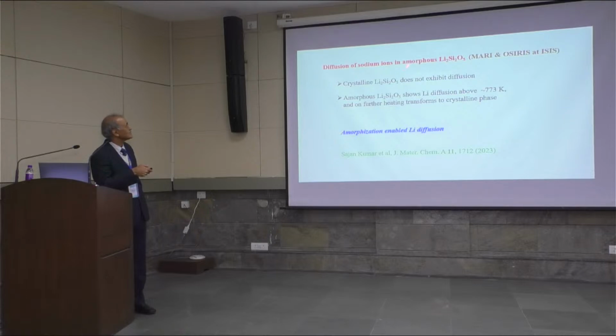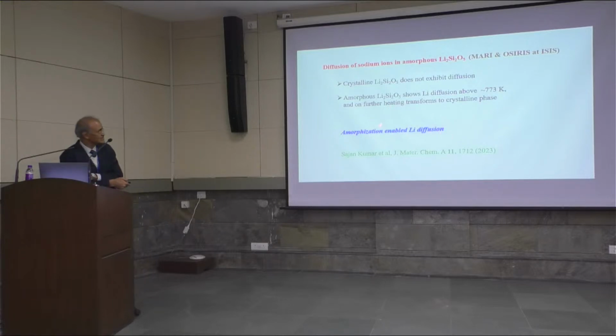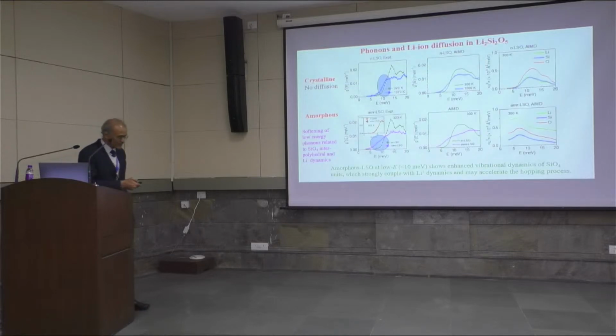There are some experiments done at ISIS, that is the Rutherford Appleton Laboratory in Oxford. What is known is that the crystalline material does not exhibit diffusion, but the amorphous material shows diffusion at some higher temperature, and on further heating, it transforms to the crystalline phase. So what we find is that amorphization enables the lithium diffusion. It's a recent publication.